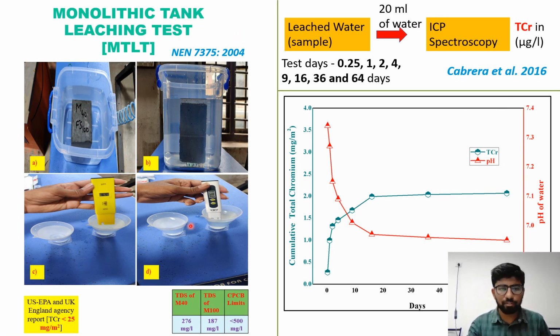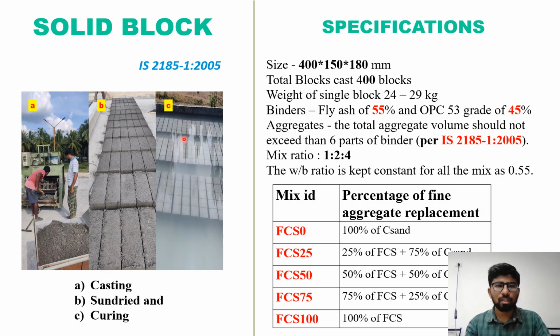Coming to the leaching study, we can see the leaching at 64 days is within the limit as per the US EPA and the UK England and Wales Agency report. So it won't cause harmful health effects to humans by leaching of total chromium. Coming to the solid block, based on the various concrete tests, we concluded that only 25% and 50% of FCS can be replaced, and we cannot replace completely. So we went for load bearing structure replacement for these various replacements.